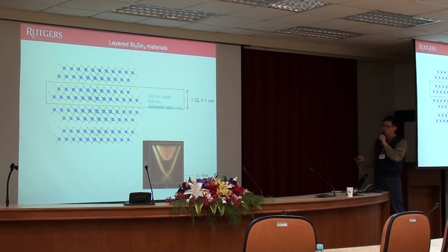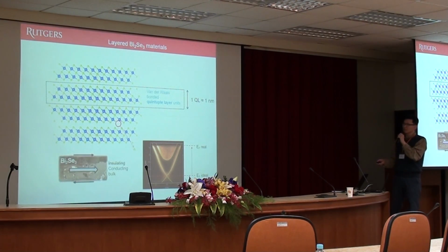Then why do we have this bulk conduction problem? In an ideal material there would not be any defects, then the Fermi level is at the Dirac point, the bulk is insulating and the surface is metallic. But the problem is, in real materials you have all these defects. In particular, because of the van der Waals bonding between the layers, the bonding energy is pretty weak, so weak that you can easily have selenium vacancies. Selenium vacancies behave as n-type dopants. So the Fermi level goes up, and it becomes metallic.